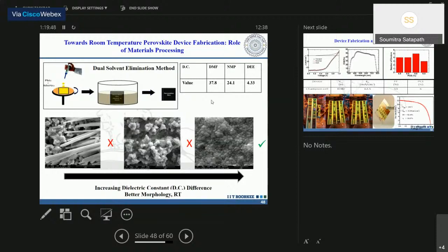Then we found that there is a trend: when we have a high difference of the dielectric constant in the mixed solvent, then we can control the nucleation and the crystal growth. When the perovskite is solvated in this DMF solvent, the nucleation starts. But when you put the second solvent there, what happens? It tries to replace the DMF and sit in that place. It hampers nucleation, so nucleation is reduced, and the crystal growth gives a larger size and uniformity.